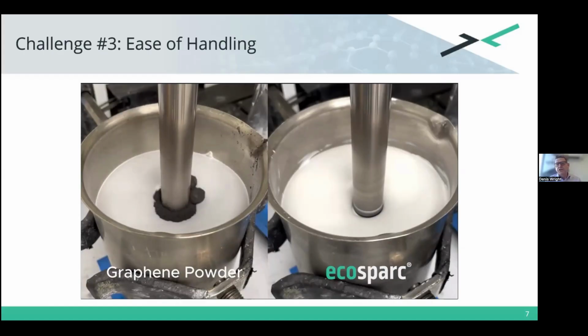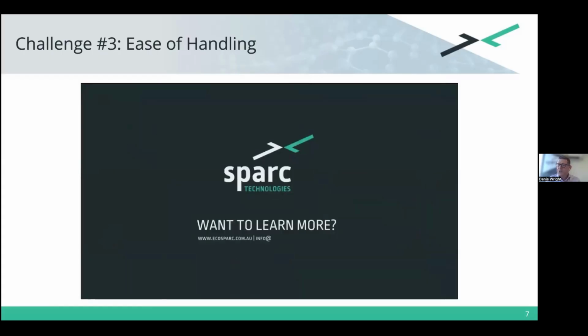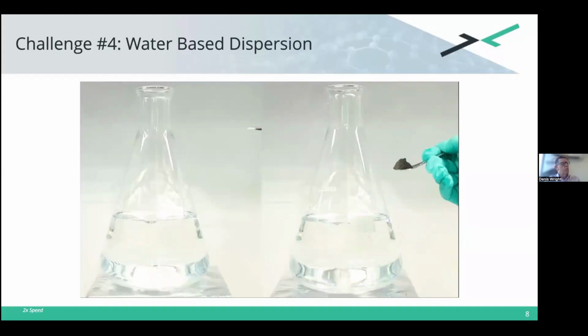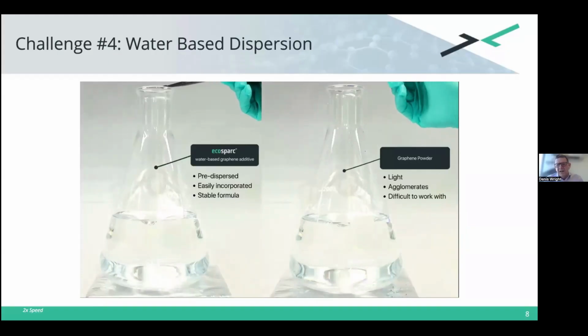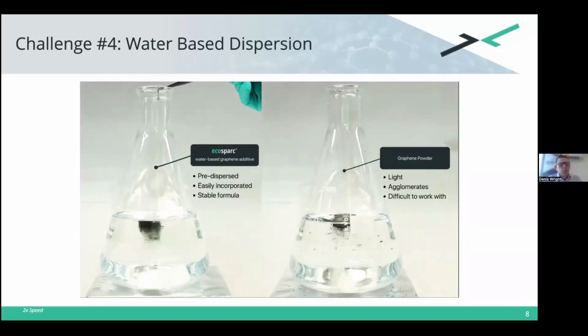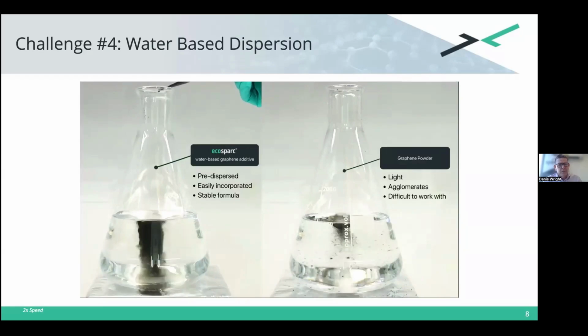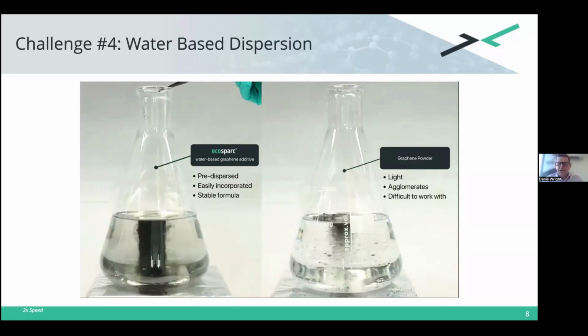Typically, the addition of our graphene-based additive is in the letdown phase or the later stages of manufacture of the coating. You can't do it as a post-add because that mucks around with the ratio of materials of the polymers in the curing in the A and the B pack. Once we've done that, for solvent-based coatings, 2 years ago, we started working on water-based materials as well.